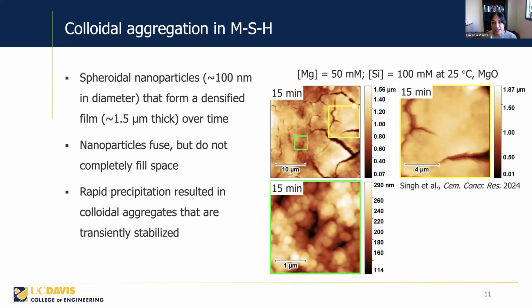We also looked at the microstructure and the morphology of this phase using atomic force microscopy. This is for a solution of 50 millimolar magnesium and 100 millimolar silicon at room temperature. This is a 15-minute reaction on the magnesium oxide substrate. What we can see is that the cementitious phases form as a densified film, which is about 1.5 microns thick, on the MgO surface. If we zoom in, you can see this yellow and then this green. Zooming in even greater detail, we can see these nanoparticles that are about 100 nanometers in diameter. These actually compose the film.